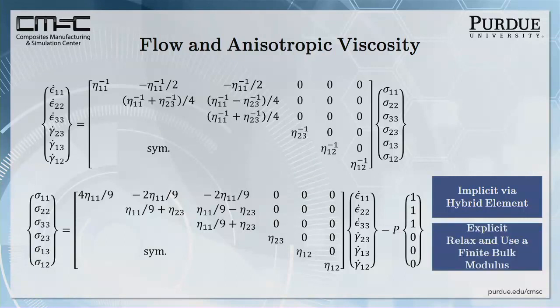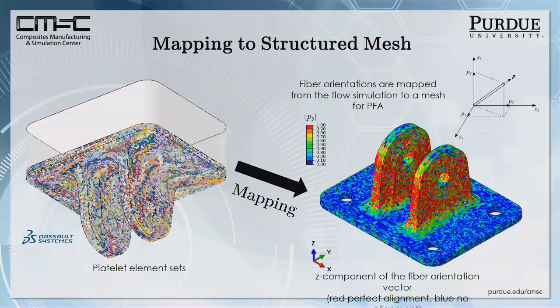We have a couple of different approaches, the implicit and explicit approaches to flow. And now you can take this data and map it into the orientation state. This is the orientation vector component in the vertical direction. If it's red, it means the fibers are pointing vertically. If it's blue, they're not pointing that way at all. They are probably lying in the plane.